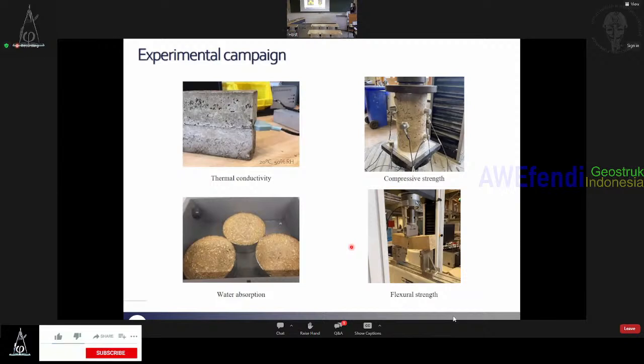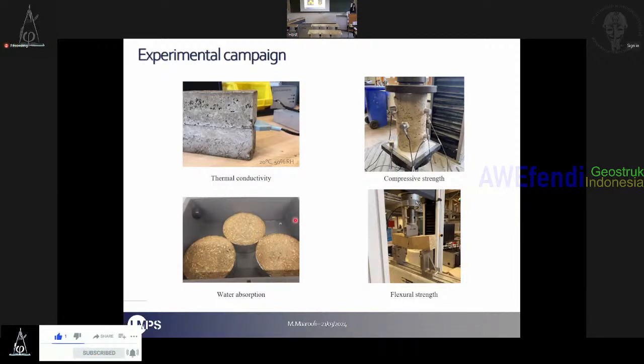Hemp concrete properties were determined before and after the accelerated aging. The thermal conductivity was determined using the hot wire method, as you can see in here. The water absorption coefficient was determined following an American standard, because we don't have a European one for this kind of concretes. Basically, the protocol was to immerse completely dried samples at 3 millimeters of height and measure the water content at different times for 24 hours. The compressive and flexural strength were determined according to the European standards.